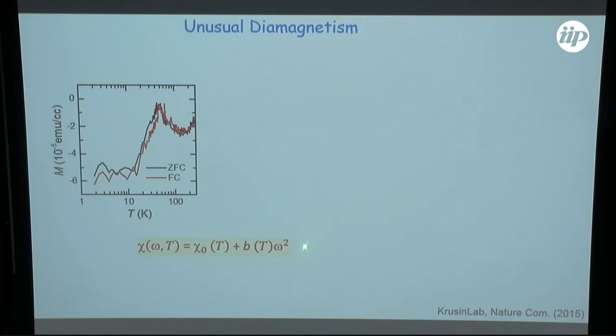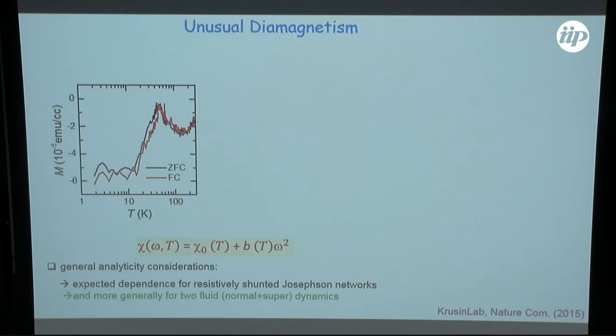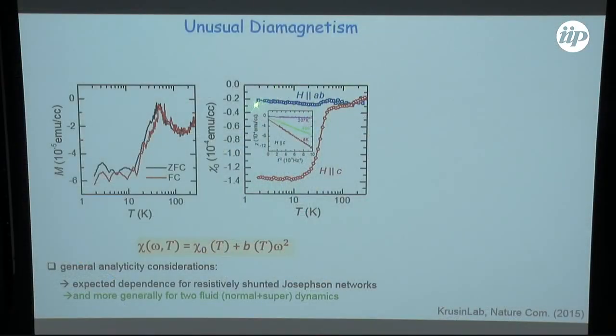by the usual omega squared dependence, which is what one would expect from a two-component system, generally for a two-fluid system, normal plus super system. And in fact, this is expected for resistively shunted Josephson junctions. And if you look at the data here for AC susceptibility and look at this frequency-independent parameter here, it shows, first of all, that unlike the critical field before, it shows huge orbital anisotropy, and again, some sort of mesoscopic Meissner transition around 60 Kelvin, consistent with what we see in DC.